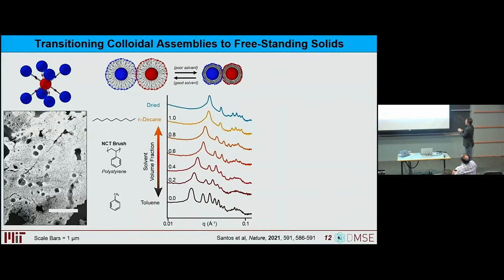What you can see is that it's the same basic crystal structure. The scattering peaks are just shifting to larger scattering angles, meaning that we're getting a smaller and smaller unit cell. By the time we get to full N-decane, we can simply dry off the solvent, and now what we have is a fully stable structure that can exist even when solvent is not present. This allows us to actually image them with electron microscopy.